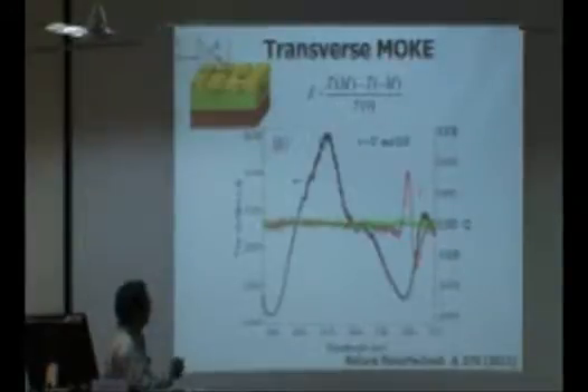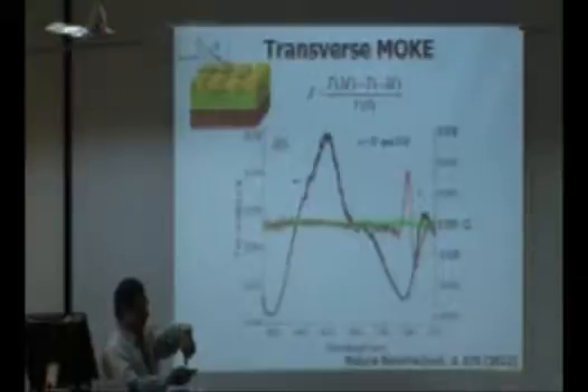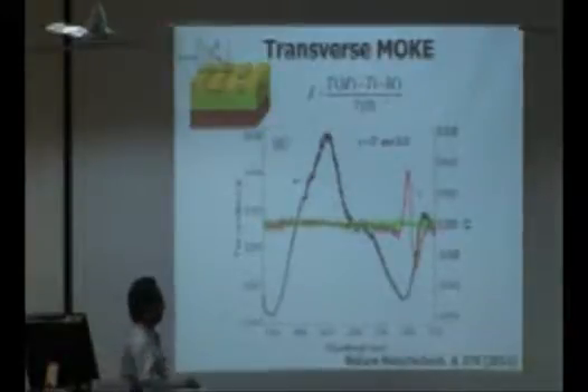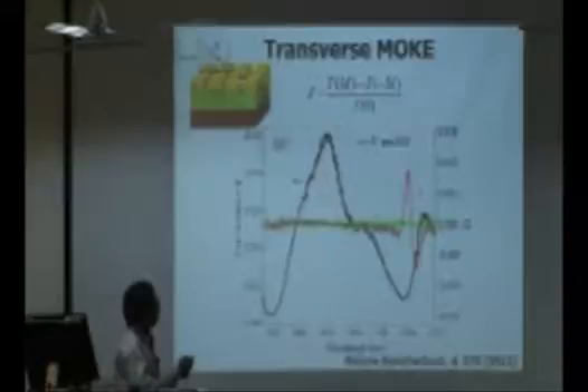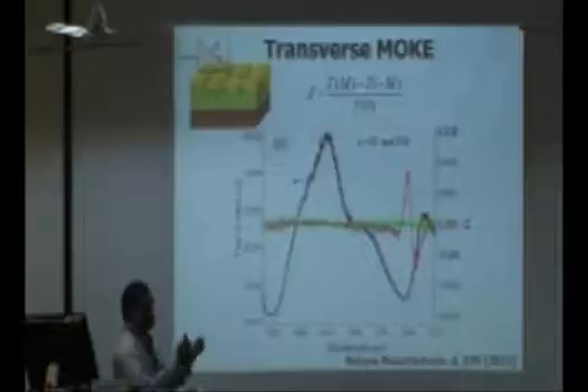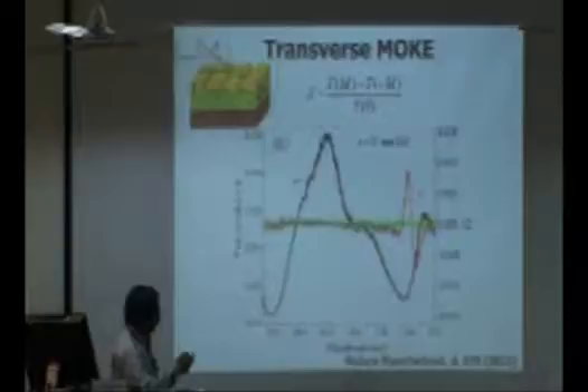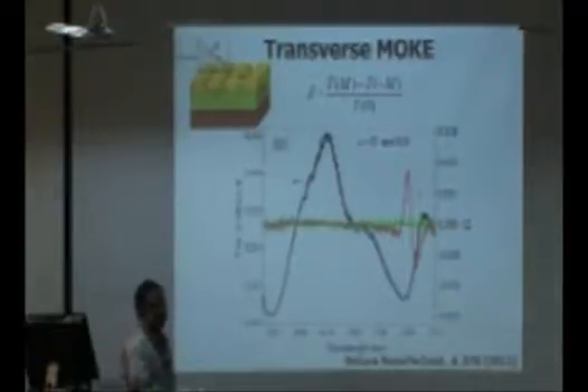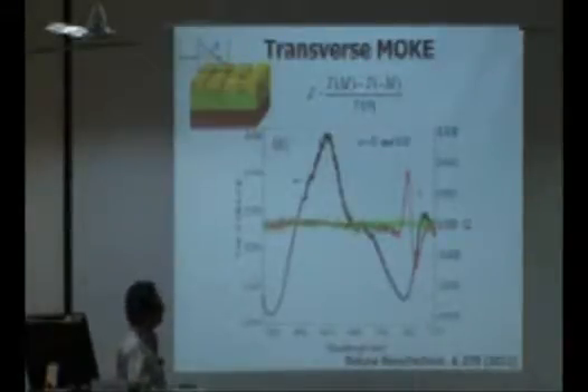But when we look at the Kerr signal for normal incidence, there are right and left circularly propagating components which form a standing wave and cancel each other. So for theta equal to 0 degrees, the green curve, there is no Kerr signal. On the other hand, if you go to a small non-zero angle like 0.8 degrees, you see a strong enhancement in the Kerr signal. You see the positive peak and the negative dip. These two correspond to the two counter-propagating waves, and they show the exact position of the plasmon resonance. In addition to the enhancement, which is 3 orders of magnitude compared to the unpatterned structures, this can be used as a precise tool to identify the plasmon resonance in these structures.